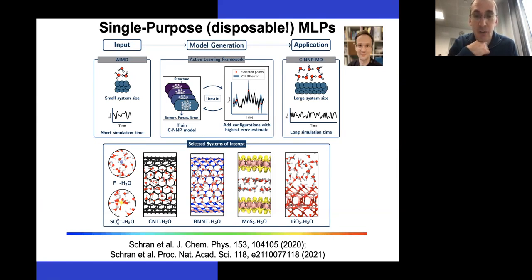this is the slide that summarizes what we managed to do and the systems we looked at. So you've seen this already. We start out with an ab initio trajectory. Then we use an active learning framework in which we train neural network potentials, and we're training potentials of the Behler-Parrinello type that you heard much more about in Venkat's lecture a month or so ago. We use an active learning framework that identifies structures that the system has not seen before, and these new structures are used